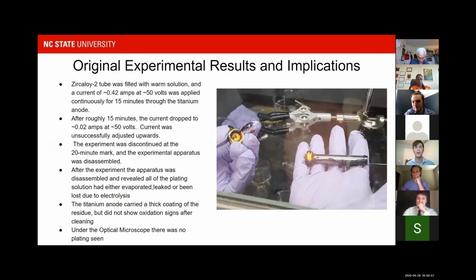For our experiment, we wanted a heated solution because we found information that says the solution plates better when it's heated up. Then we had to set a current of approximately 0.42 amps and a voltage of about 50 volts. It's approximate because the solution is getting heated and then cooling, so the resistivity and such will change with time. But we had ways to measure it.